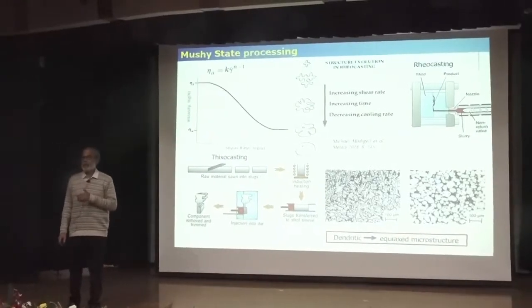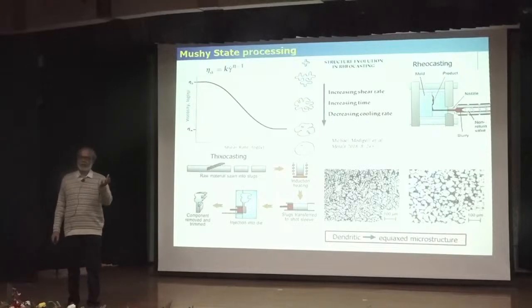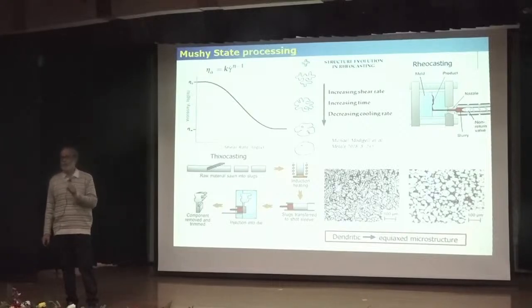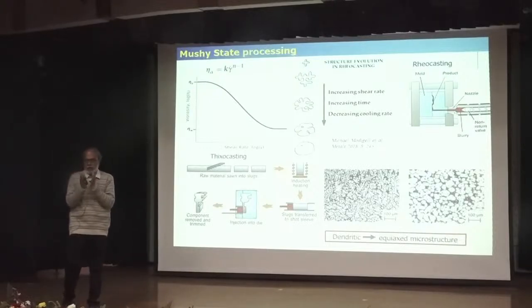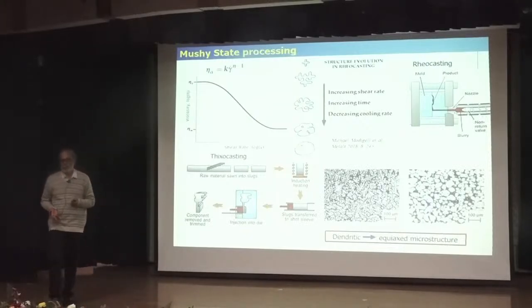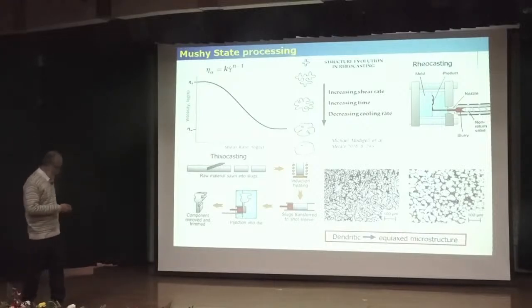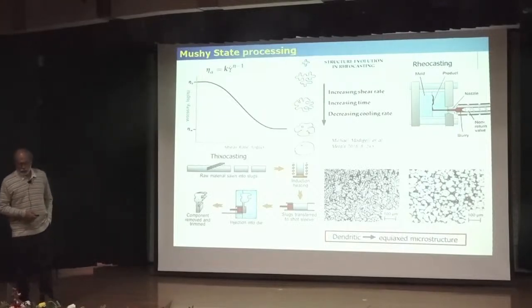Now here, some more parameters came into the scenario apart from the shrinkage of the liquid, behavior of gas, and convective percolation of liquid within the dendrite. It became the behavior of viscosity and stress of the liquid. So the constitutive framework of semi-solid casting is really complex, and it needs a strong mathematical framework to predict some outcome. And many people are now working in this area, so they are coming across such difficulties, but in the end, we can get rid of dendritic and columnar microstructure, and we can produce equiaxed microstructure. And by that, we can eliminate another step of heat treatment.